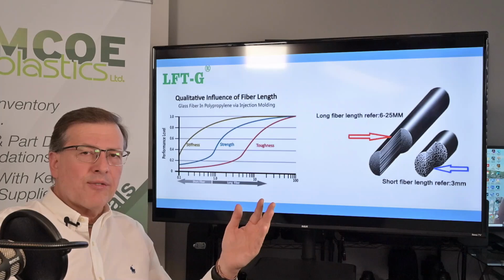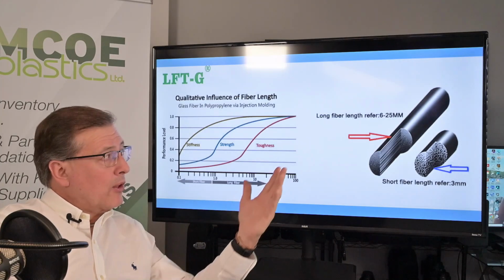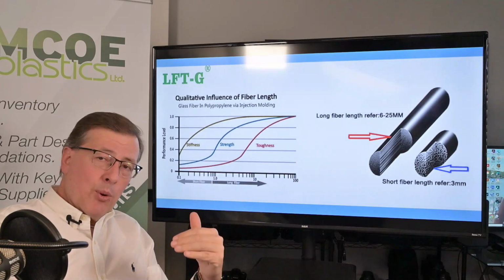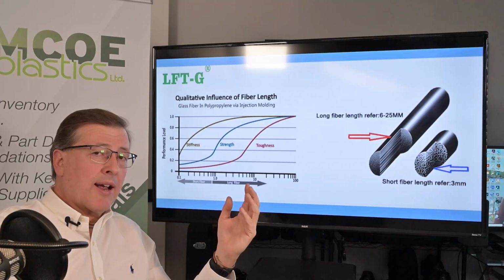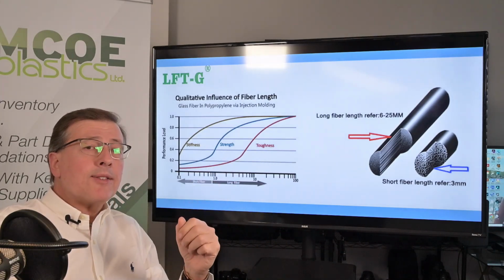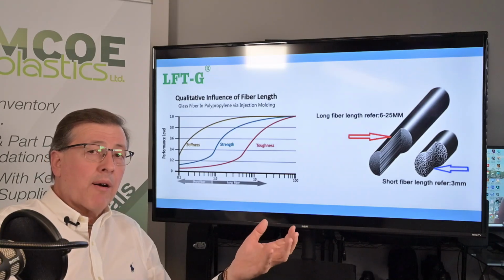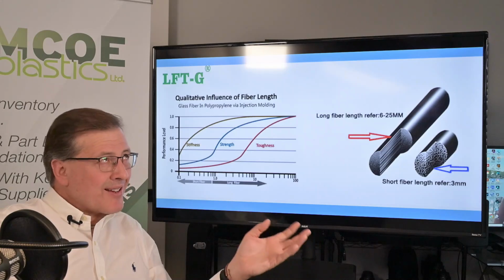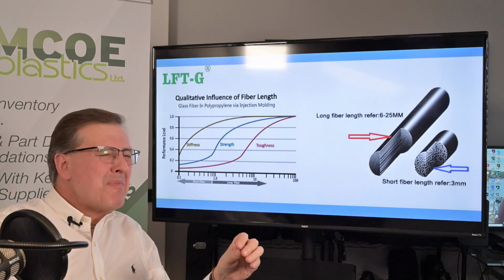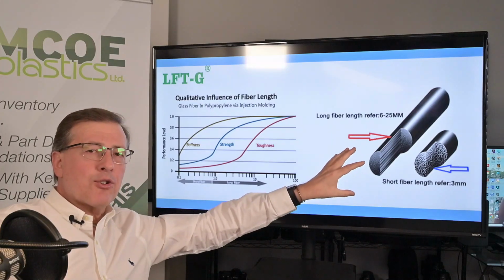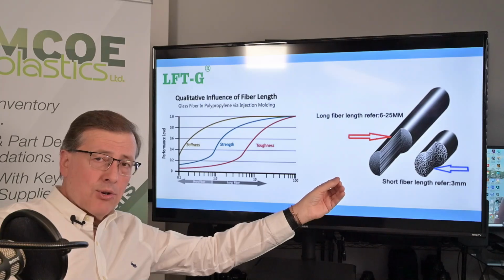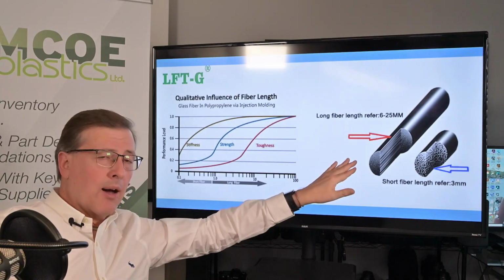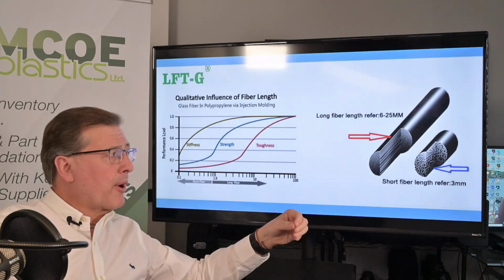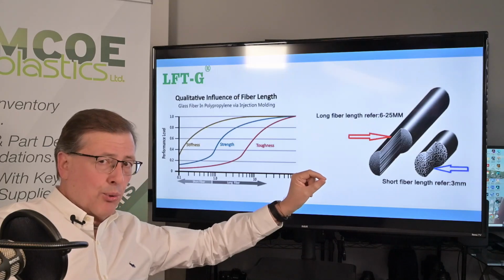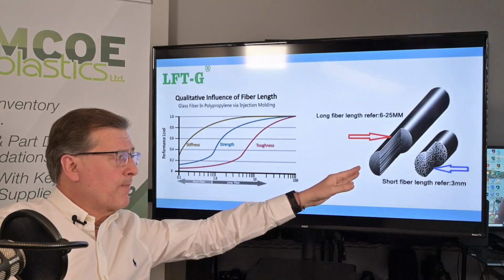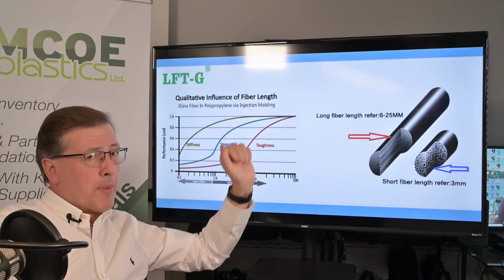If you're using a more expensive kind of esoteric type of engineered resin, a long glass nylon or a long glass polypropylene may give you a cost down. Plus, you've got the familiarity of running a more conventional commodity-based resin, the carrier resin, instead of something like a PPS, which may require an oil heater on the mold, where you get into elements of complexity, and there's maybe some concerns about safety as well. These are very conventional in terms of how they run. You do have to have some tooling considerations. Sprue and runner and gate land, that kind of thing has to accommodate a long glass pellet, and you have to work with your tooling partner to identify the special needs that that particular tool and part will have to accommodate this type of material. So where are you going to use it? As a cost down from a higher end resin.